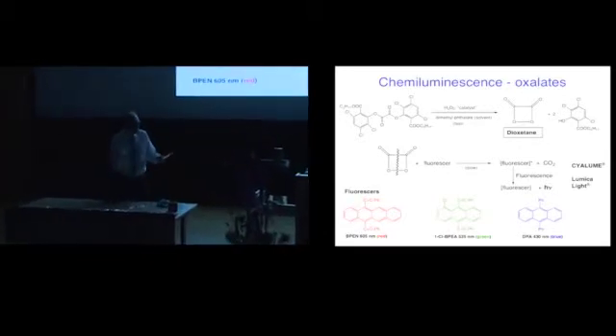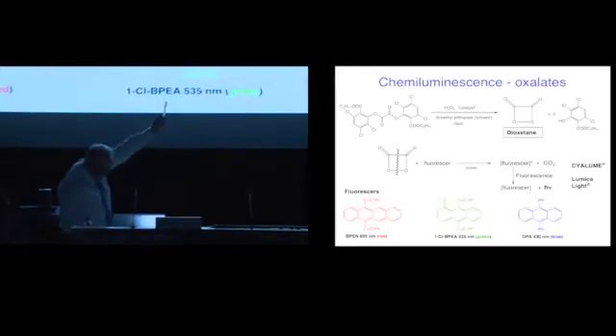And we'll leave the lights down still, but I want to now demonstrate that with a blue light stick with a stronger ultraviolet light. And see, this tube is almost transparent, but if I now irradiate it with ultraviolet light, it will fluoresce in the blue. And you can see that. Very strong blue fluorescence. By the way, the whitener in this white shirt is also a blue fluorescent material, much better actually than the blue in this. So that's how we can do the lights up.